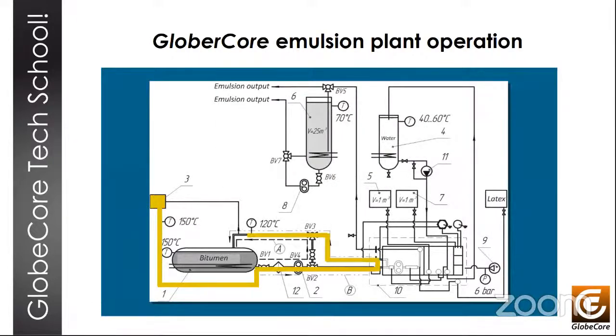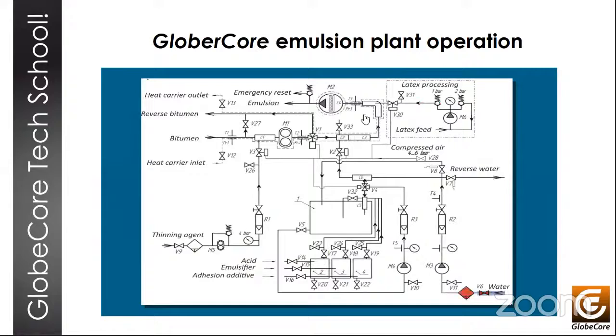So let's look at the operation of this machine. Before everything starts, everything is warmed up to 110 degrees Celsius with the oil of the heating system that's provided by the heating station. All right. In the boiler, the bitumen boiler, bitumen is heated to 140 to 160 degrees Celsius. In the water tank, water is heated to 40 to 60 degrees Celsius and is supplied to the plant through an inlet filter. The water pump's turned on, and the water goes through the flow meter, a control valve, and it's circulated to stabilize the temperature in the water heating tank.